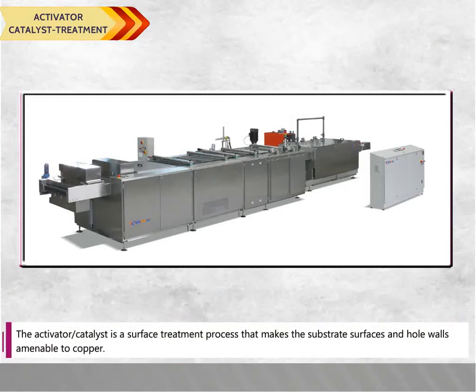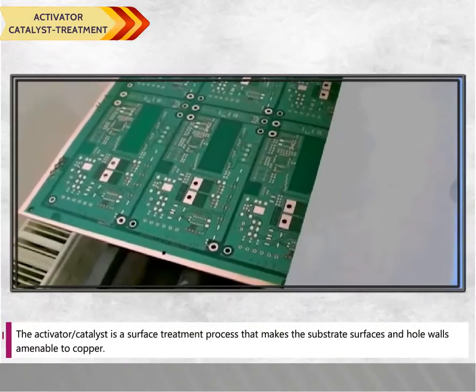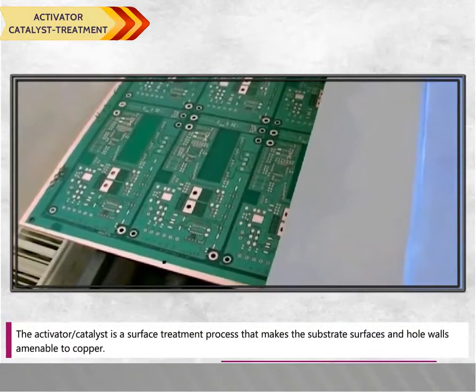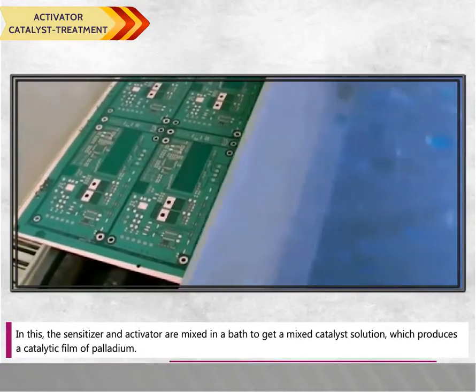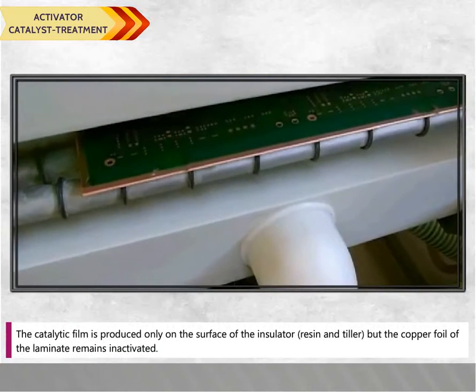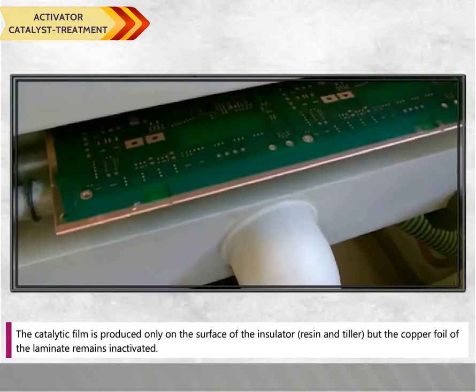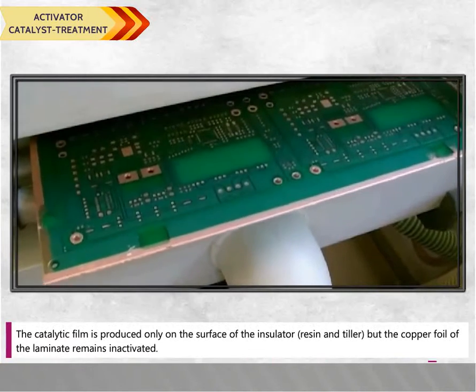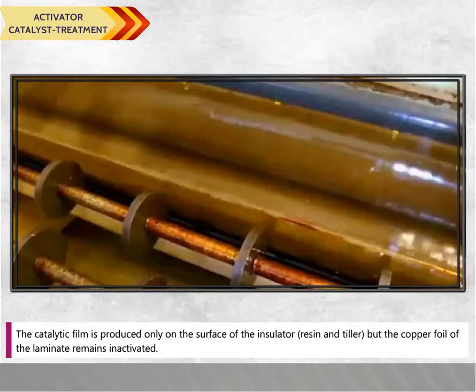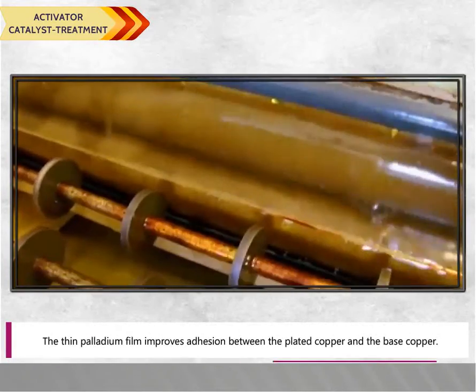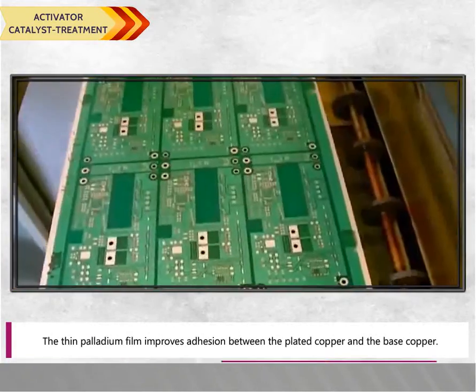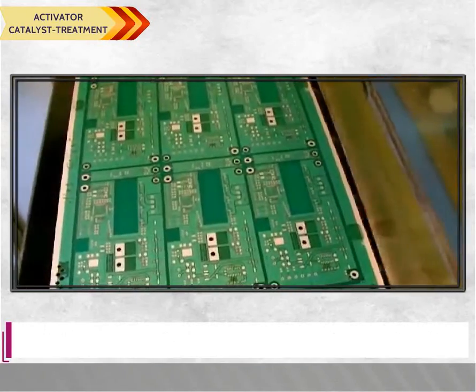Activator catalyst treatment. The activator or catalyst is a surface treatment process that makes the substrate surfaces and hole walls amenable to copper. In this, the sensitizer and activator are mixed in a bath to get a mixed catalyst solution which produces a catalytic film of palladium. The catalytic film is produced only on the surface of the insulator, the resin and filler, but the copper foil of the laminate remains inactivated. The thin palladium film improves adhesion between the plated copper and the base copper.